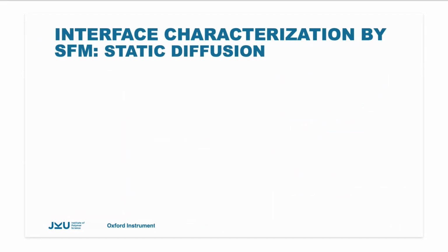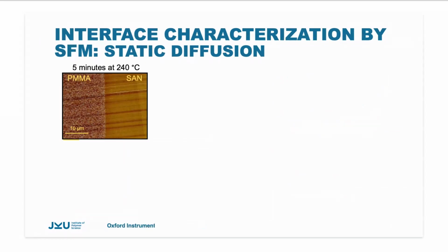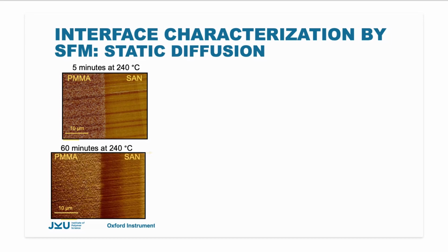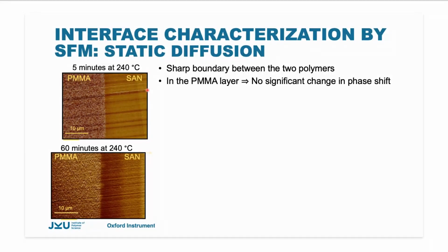Now, how does our interface look after static diffusion of 5 minutes at 240 degrees and 60 minutes at 240 degrees? First thing that can be seen is that there is a sharp boundary between the two polymers, the PMMA and the SAN. Second, at the PMMA side, we do not see any significant change in the phase shift, even at the boundary. While on the SAN